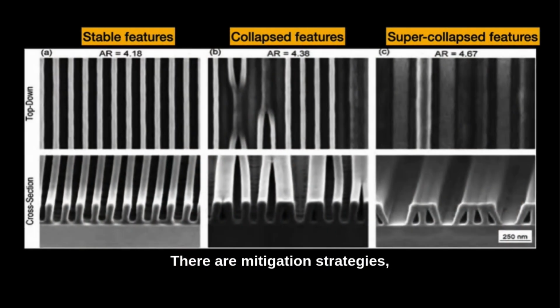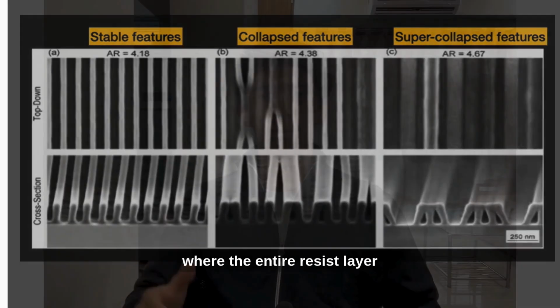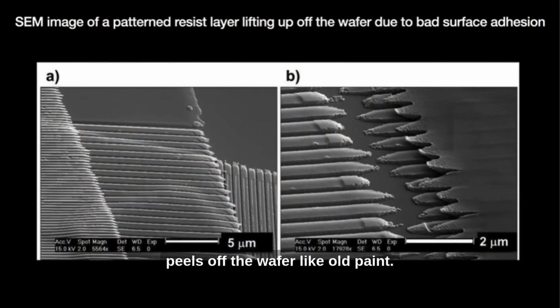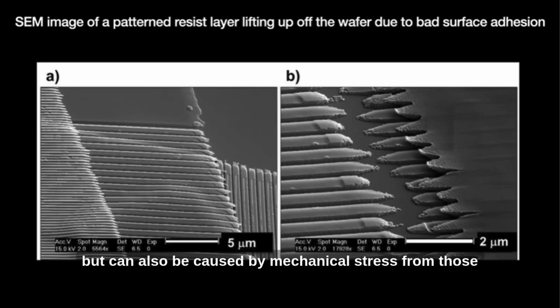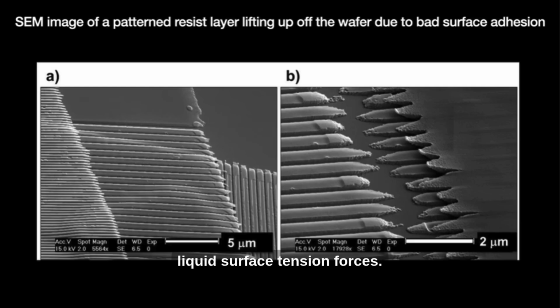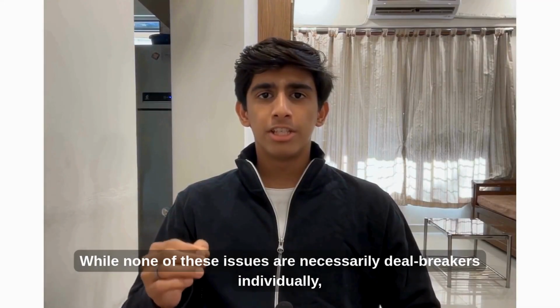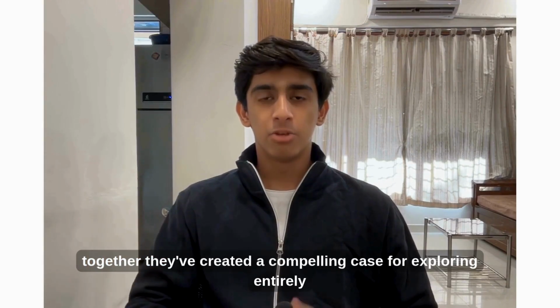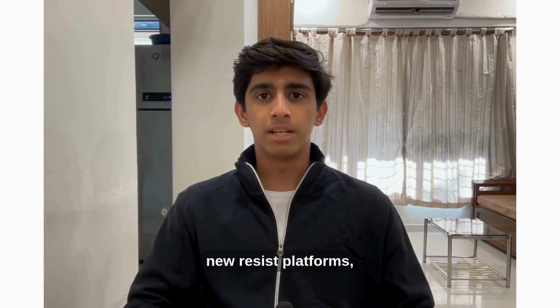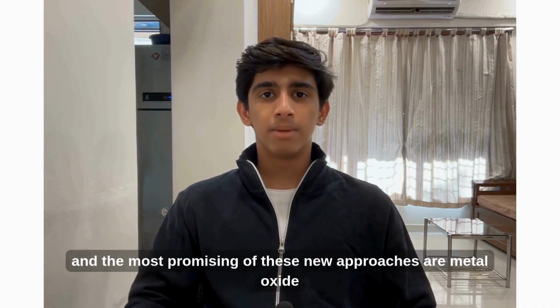There are mitigation strategies, adding surfactants to the rinsing liquids or using supercritical carbon dioxide for drying. But these introduce their own risks, including swelling or shrinking of the features. Another related concern is substrate delamination, where the entire resist layer peels off the wafer like old paint. This is usually due to poor adhesion between the resist and wafer surface, but can also be caused by mechanical stress from those liquid surface tension forces. While none of these issues are necessarily deal breakers individually, together they've created a compelling case for exploring entirely new resist platforms. And the most promising of these new approaches are metal oxide resists.